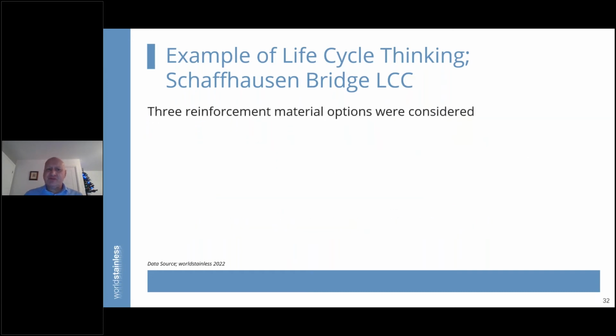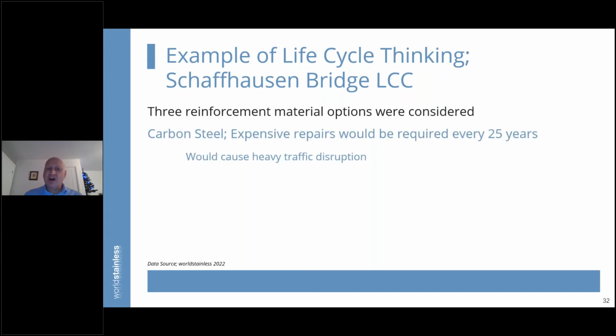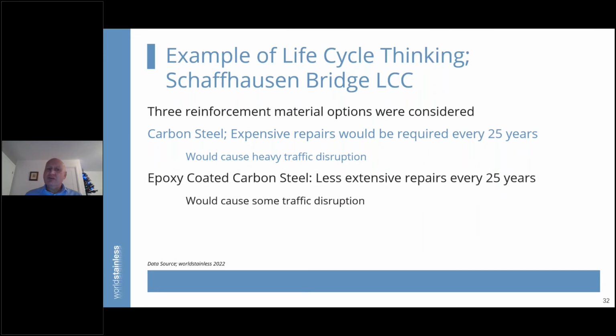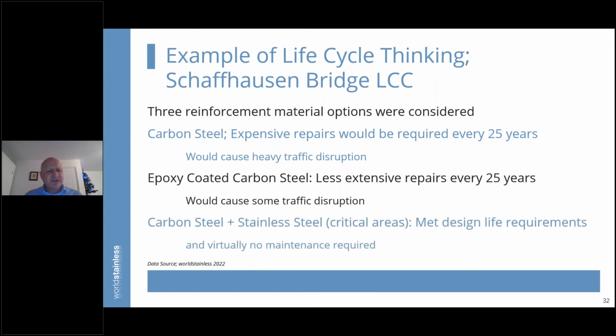So 3 reinforcement material options were considered for this bridge. Carbon steel. Choosing carbon steel would have meant that expensive repairs would be required approximately every 25 years, and the effect of that would be massive or heavy traffic disruption. Another option, epoxy coated carbon steel. Less extensive repairs, but still every 25 years. And that's because the epoxy coating would degrade and start the corrosion of the carbon steel. And that would cause some level of traffic disruption. And the third choice was using carbon steel plus stainless steel in critical areas. And without a doubt, that met the design life requirements and virtually no maintenance required as well. So it ticked both boxes there, quite interesting.